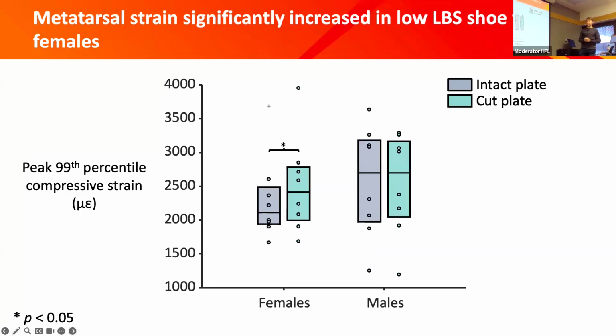So what we wanted to do is actually split it one step further into the female group and the male group to see if there was a change happening because of sex. And we actually did see something cool. We saw a significant increase in that peak 99th percentile strain in females in the cut plate shoe, and we saw no change in the male group. So where is this change coming from?